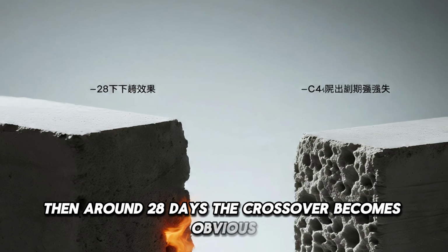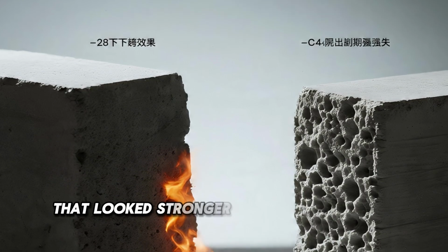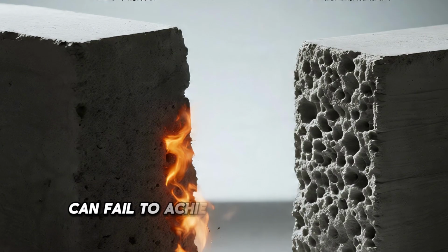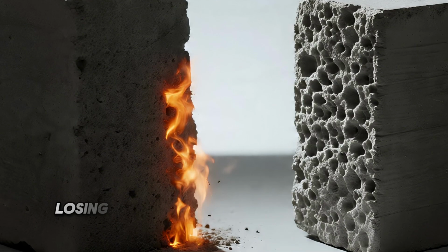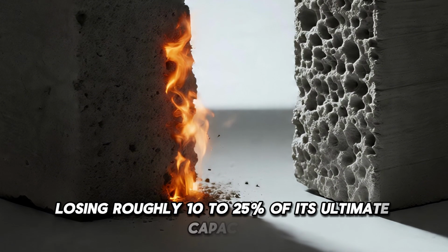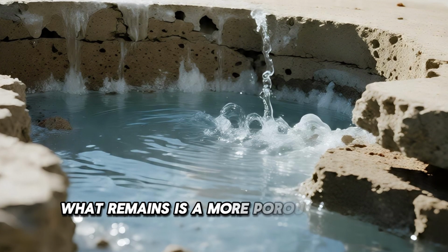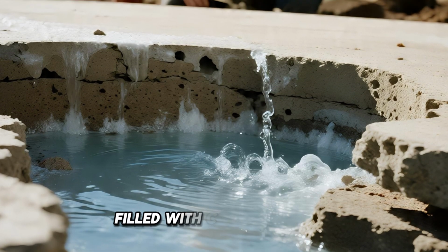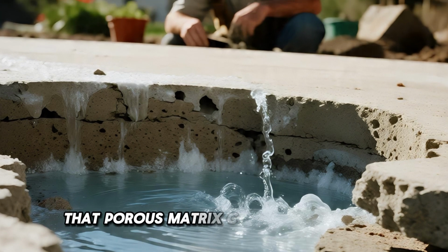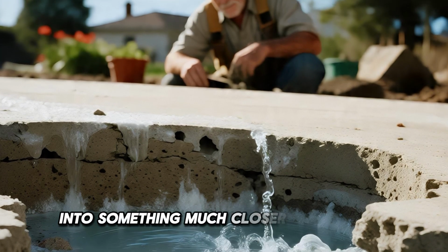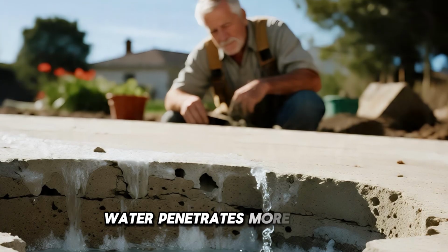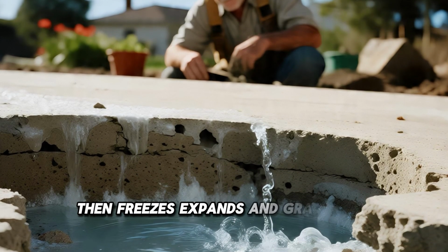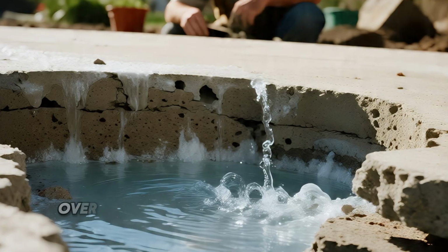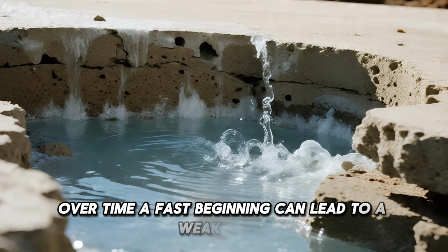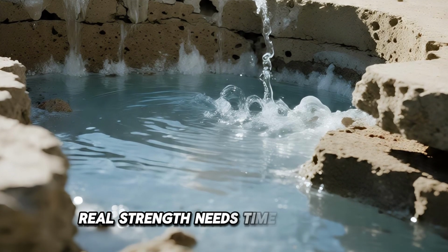Then, around 28 days, the crossover becomes obvious. The concrete that looked stronger during its first few days can fail to achieve its intended design strength, losing roughly 10 to 25% of its ultimate capacity. What remains is a more porous internal structure, filled with capillary voids. That porous matrix can turn your slab into something much closer to a sponge. Water penetrates more easily, then freezes, expands, and gradually damages the surface over time. A fast beginning can lead to a weak finish. Real strength needs time to develop.